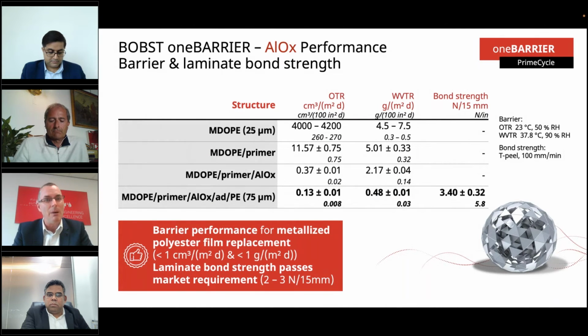So with that, let's now have a look at the full performance of the one barrier duplex solution. If we start with the transparent AlOx structure and look at the performance through all conversion steps, we start with the MDO-PE film that has an oxygen barrier of around 4,100 cubic centimeters per meter squared per day and a water barrier of 6 grams per meter squared per day.